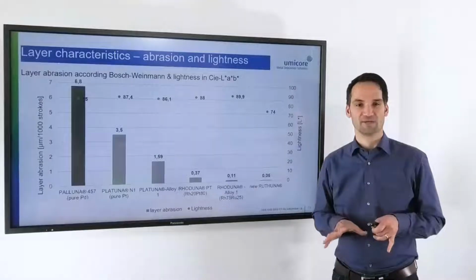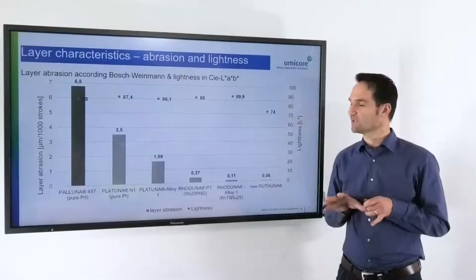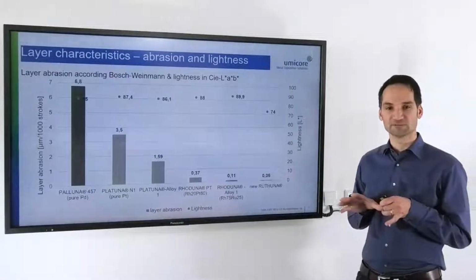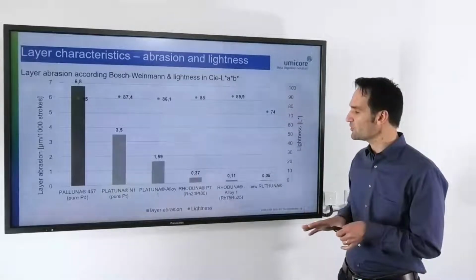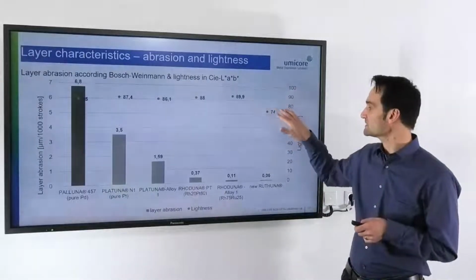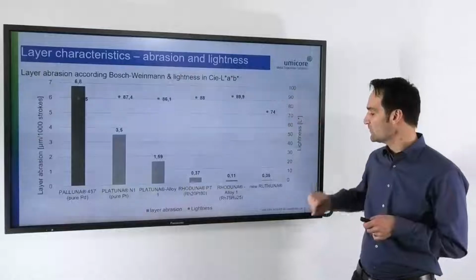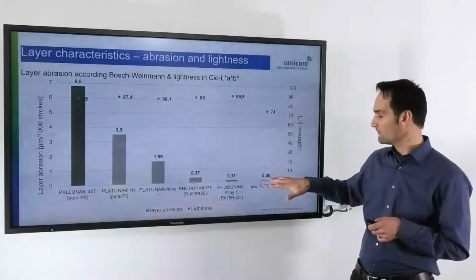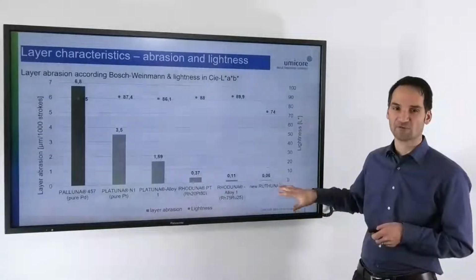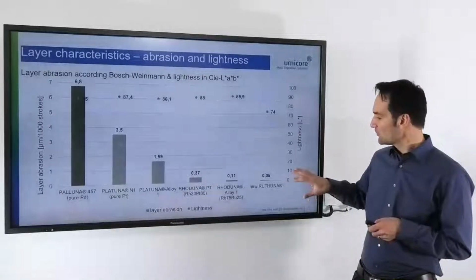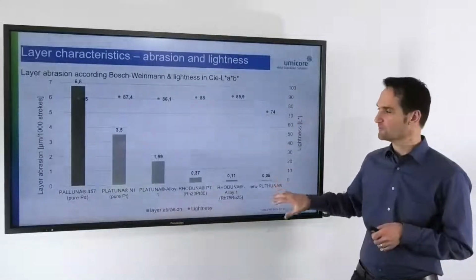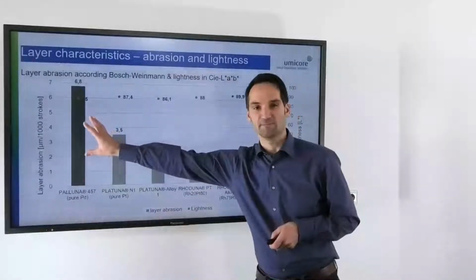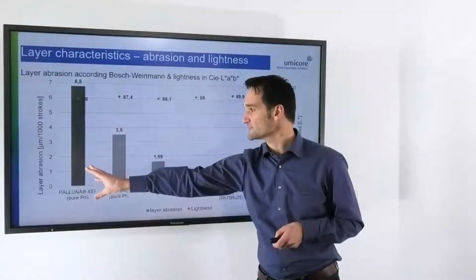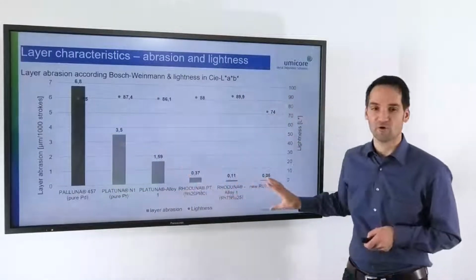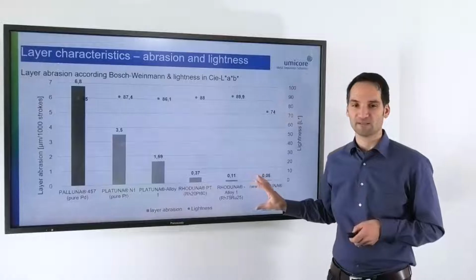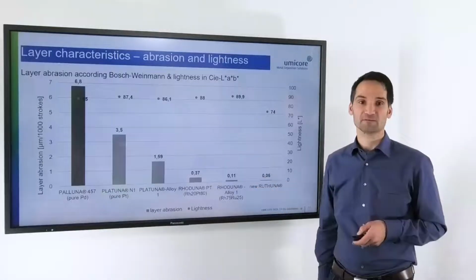What is the advantage of such layers? The new ruthenium brings you a lot of benefits. The major point is, at a lightness of 74, you have an abrasive resistance of 0.06 micron at 1000 strokes. Compare this very good abrasive resistance with palladium, which is actually very soft, and even compared with all the other platinum group metals, it is even better than rhodium.